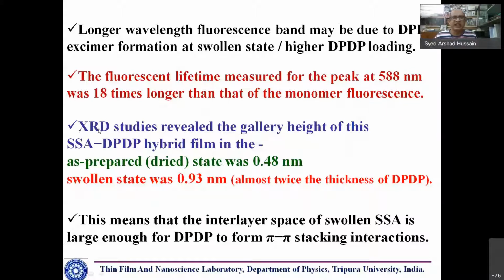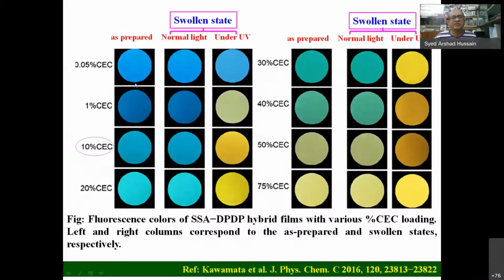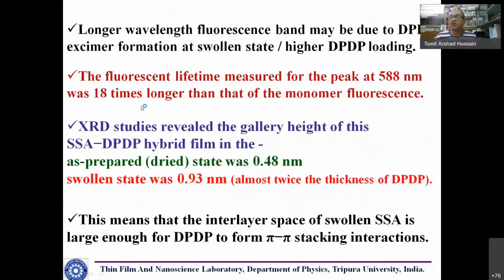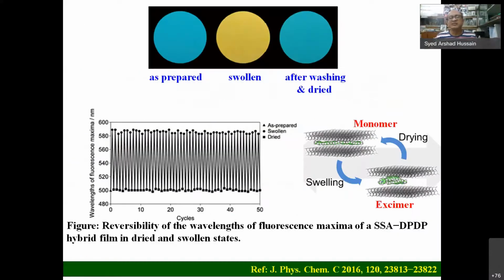Also, we studied XRD and measured the gap between the layers, and we have seen that when this film is dry, the gap is of the order of 0.48, but when it is swollen, the gap is 0.93. So this is almost double the single thickness of the molecule. So we consider that pi stacking under swelling conditions forms an excimer. And you know, an excimer is an excited state phenomenon because it involves one ground state and one excited state molecule. So only the fluorescence color change occurs, not in absorption. So to the naked eye, no color change.